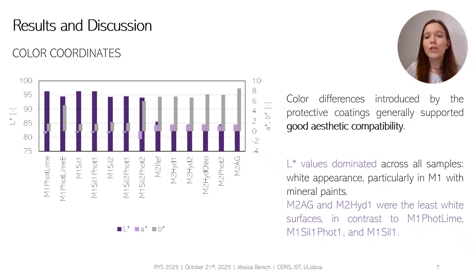These are the color coordinates of the different surfaces studied in their original form. What we have observed is that the color differences introduced by the protective coatings compared to the original mortar substrate or the silicate paint, for example, generally supported good aesthetic compatibility. This means that the hydrophobic coatings or the photocatalytic ones, for instance, do not induce great color changes compared with what was there before.